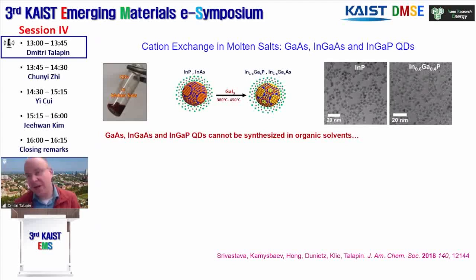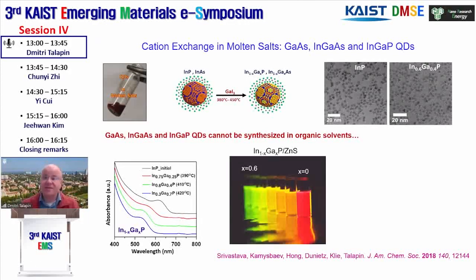What we learned over many years of exploration is that we now have amazing methodology for indium phosphide and indium arsenide synthesis, but we couldn't make gallium-containing materials, for a number of reasons. First, gallium is very oxophilic. Second, gallium(III) is too strong a Lewis acid, and it does side reactions at high temperatures, such as C-H or beta-hydride elimination, C-H bond activations. So we had severe problems synthesizing gallium-containing quantum dots